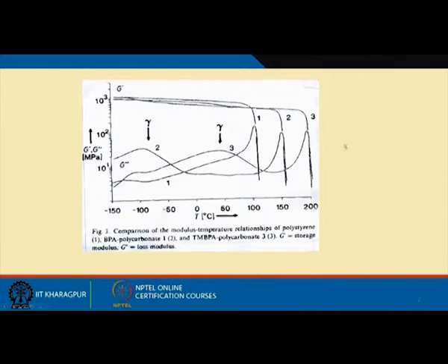So, that is why this experiment, the dynamic mechanical analysis, can tell you about the glass transition temperature also. So, you see that for bisphenol A polycarbonate, it is around 150 degrees Celsius, and interestingly there is a bump somewhere here which is very important. We will talk about it after. And when you are talking about your tetramethyl bisphenol A polycarbonate, again G prime is very similar, it goes down at a higher value of temperature, 200, which tells you the glass transition temperature is around 50 degrees Celsius higher than your parent bisphenol A polycarbonate, and this is your loss curve. So, this is 3.